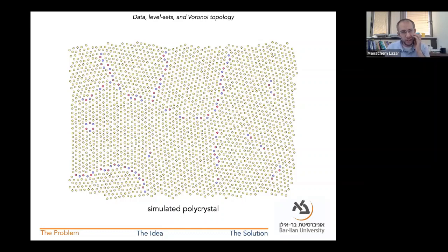Now, even to do experiments of this sort in a lab is expensive, is laborious. So what a lot of the scientists do, computational material scientists and computational physicists, they'll use big computers to simulate these systems. They might use what's called molecular dynamics. They'll solve Newton's equations of motion for all the particles, and they'll heat the system in a certain way and see what happens. How do the defects propagate? If you apply a certain stress to the system, what happens? Can you make them disappear?